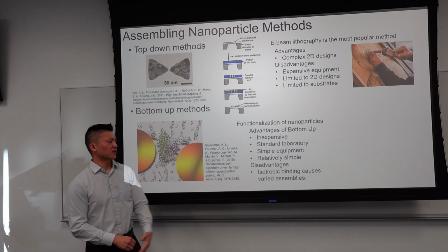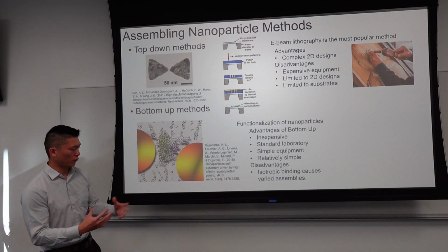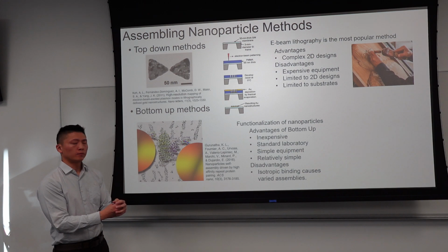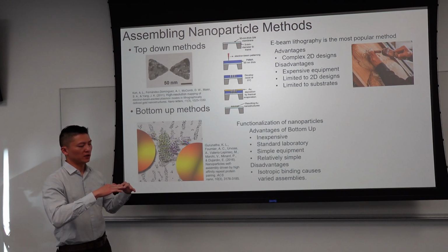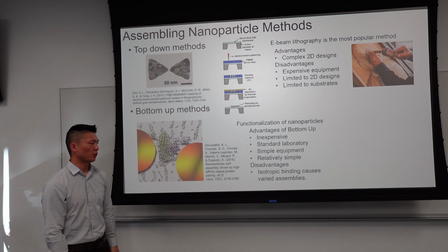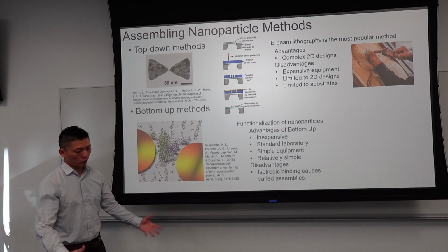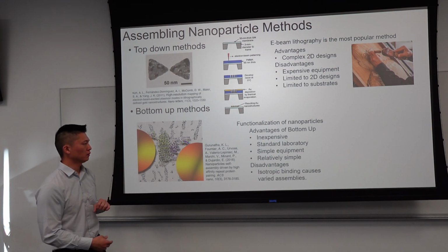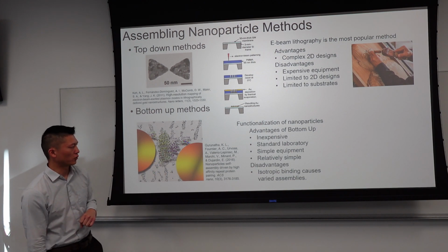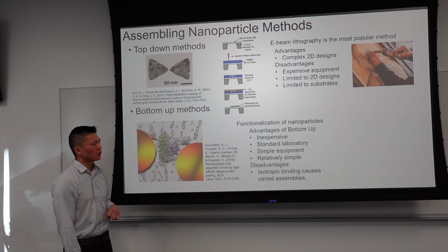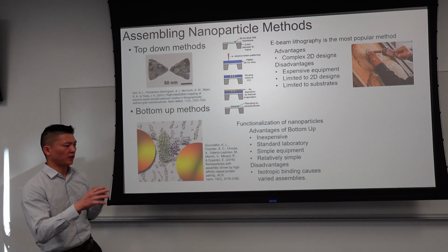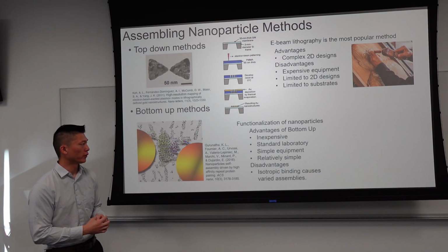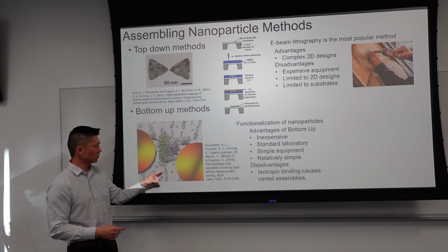Again, there is a disadvantage, and that disadvantage is that with nanoparticles, we use ligands to functionalize a nanoparticle, and the ligands tend to create a shell around the nanoparticle. That would mean that if there's binding between ligands, like I'm showing here, two proteins binding to each other, the binding is isotropic. They can approach each other in different directions, and the shell of the ligands can bind with one another.